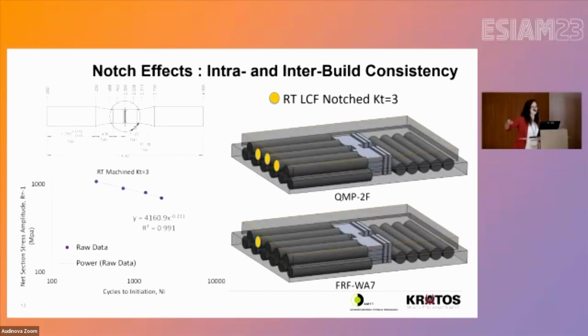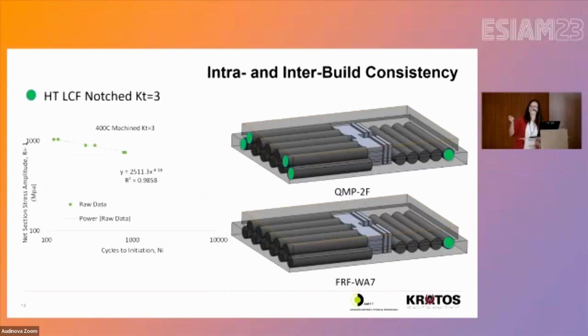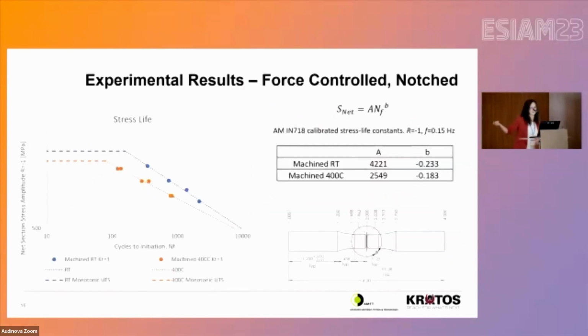And so you basically take the same approach. However, because these are not specimens, these will now be in a load control regime rather than strain controlled, as is typical. So once again, you go and make your specimens, you perform your tests, and you decide, oh, did I do a good job? And when your process controls are sufficient, yes, you'll get a sufficient response is our claim.